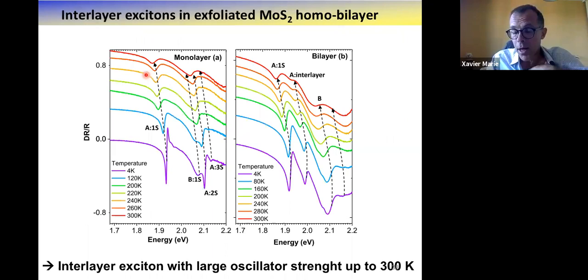And indeed, when you perform this experiment as a function of temperature, you clearly see, here for the monolayer, again the A and B exciton, how it changes with temperature from 4K to 300K. And here on the right, the same for the homo bilayer. So at low temperature, I already showed you the A and B exciton, and between them the transition we assign to the interlayer transition. And when we increase the temperature, you clearly see that you keep this transition even at room temperature.